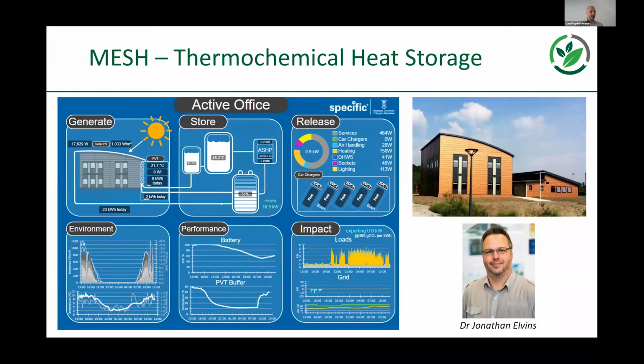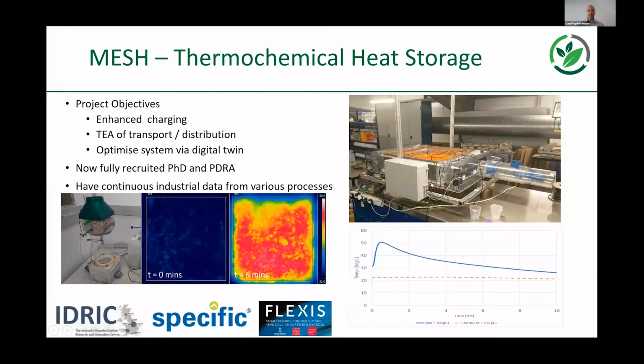And then very finally, with my last 50 seconds, I just wanted to highlight the work of Jonathan Elvins. He's done this really interesting work developing a heat storage material, which is essentially a salt-in matrix material, which if you pass warm, dry or hot, dry air over it, will charge endothermically and then discharge exothermically when you provide cool, damp air, which we have lots of in Wales. He's done that in the context of active buildings already, but now what we're looking at doing is seeing how we can tailor that specifically to get heat storage from the steel industry.